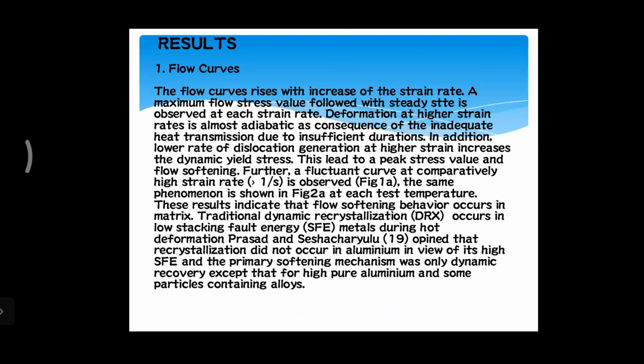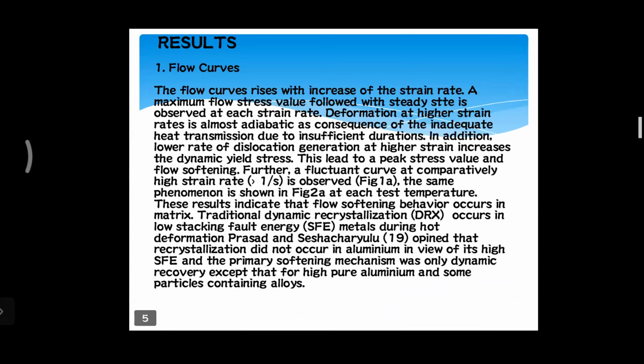And in the second graph, the third one, is the 7178 10% SiC composite at 100 degrees centigrade, and similarly at 400 degrees centigrade. The lower curves are for the composite and the upper ones for the alloy material. Roughly, on increasing temperature the flow stress decreases, and on increasing strain rate the flow stress increases. These are the two interpretations we get from these curves.